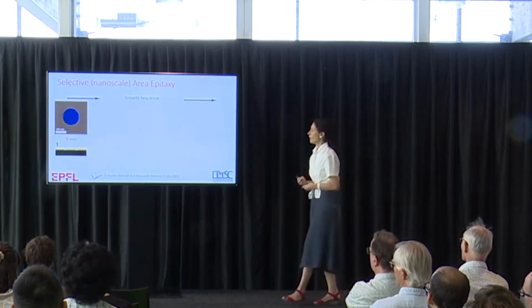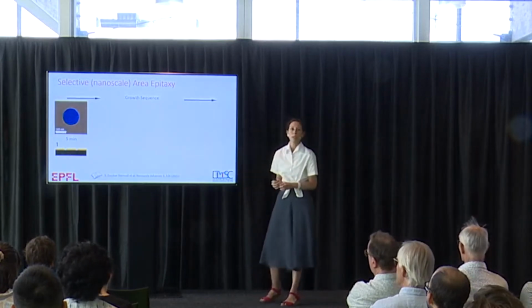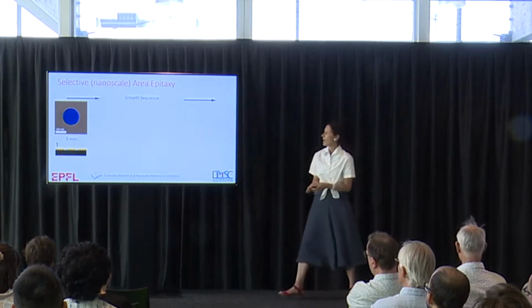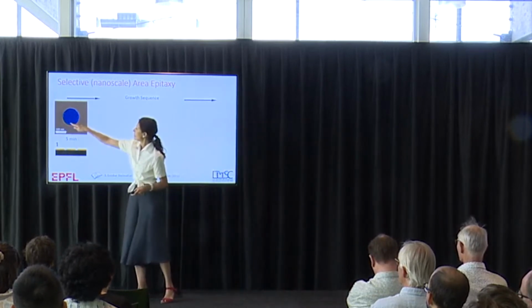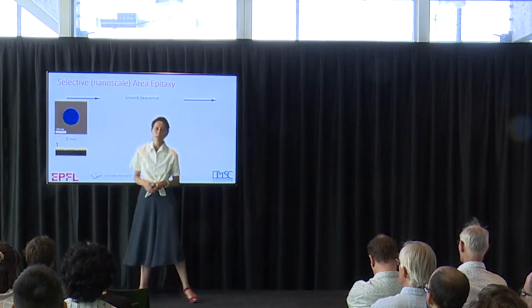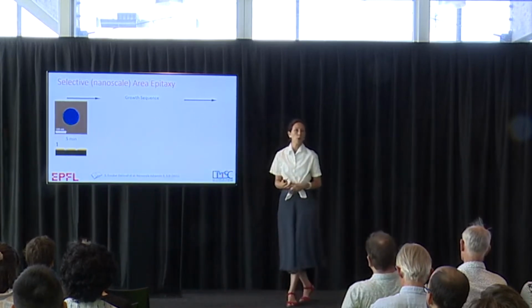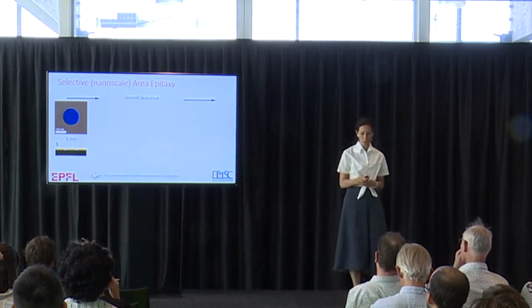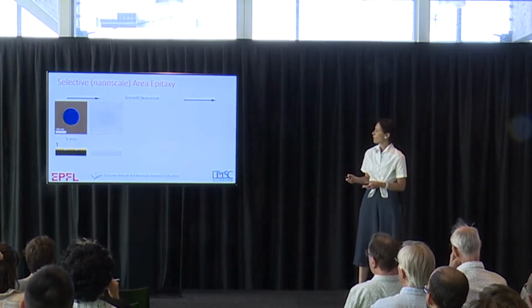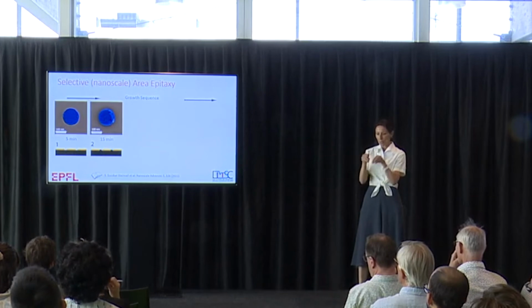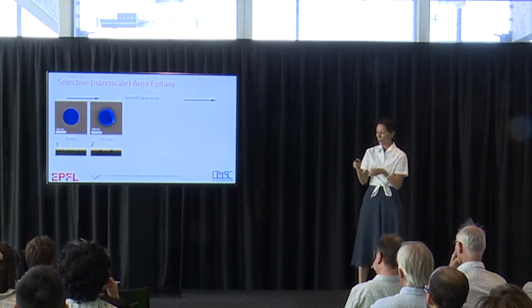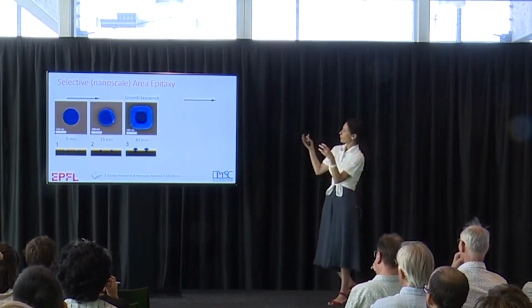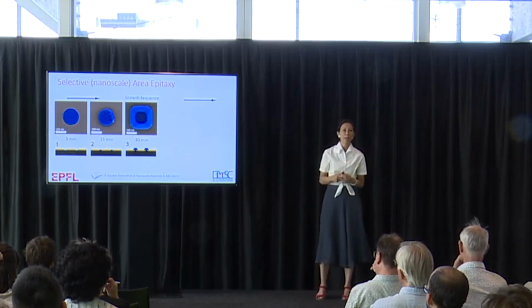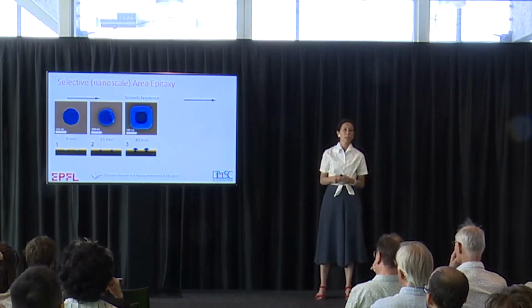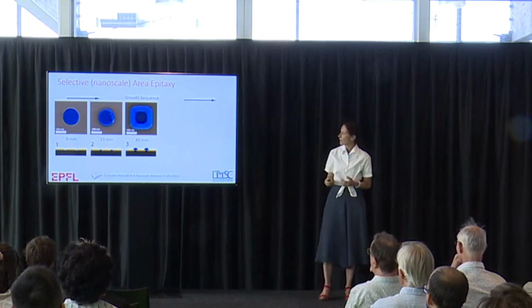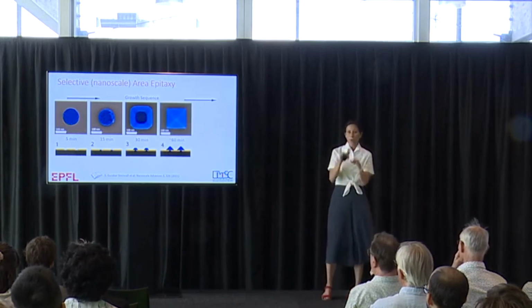So we started growing in a nanoscale hole. You would think that if you have a mask, here's the oxide, and this is a nanoscale hole where growth starts, that we want to grow a nanowire, but in fact we achieve something else. When you look at it as a function of time, you start having small islands that join, and when they get out of the hole, they start creating a pyramid. This pyramid is formed by surfaces that have the lowest energy. And here you see a bit later in time how this pyramid has formed.